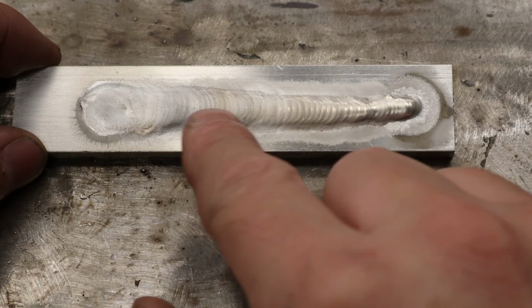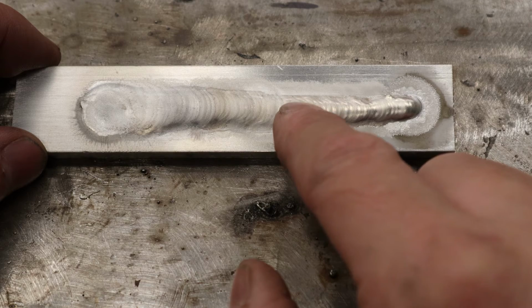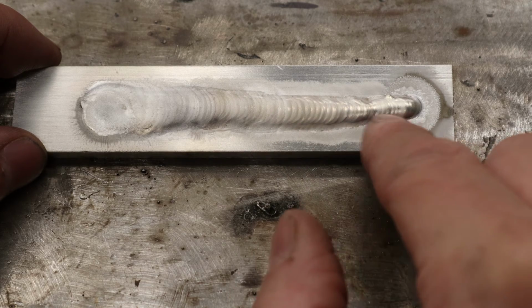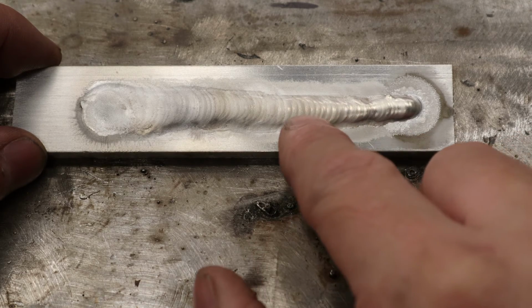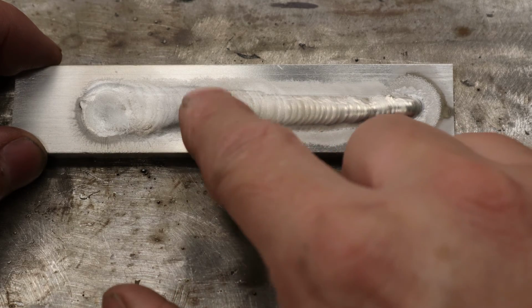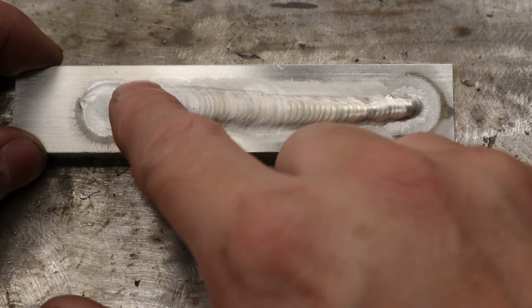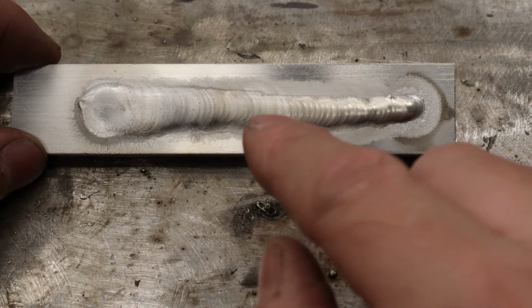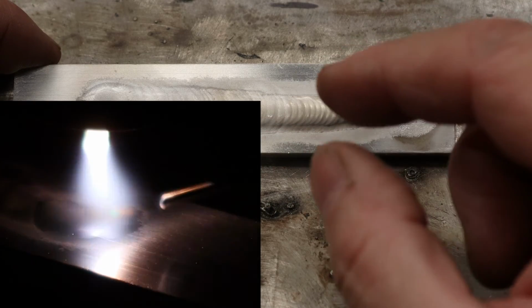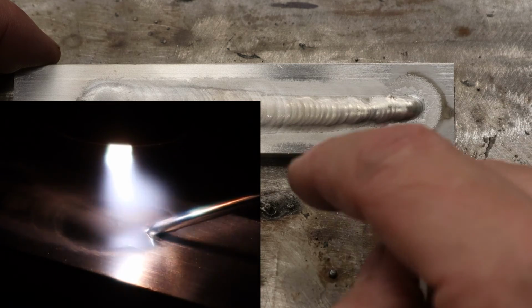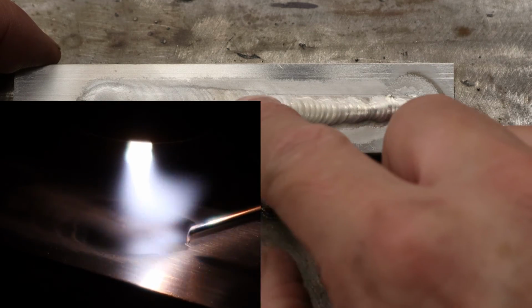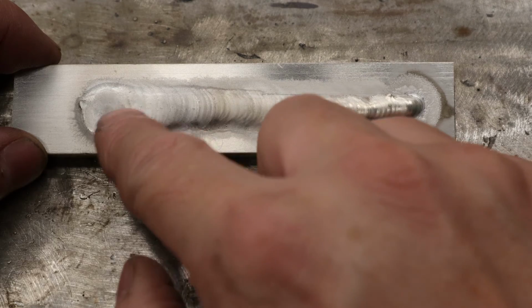And as it starts to go that way, we start to have not as much gas coverage. So you can start to see the shine of the weld start to fade. And it gets a little bit more grainy in here because we just don't have that gas coverage. And the other thing that hopefully the video picked up, there is a little bit of loss of control because the further away the arc has to jump, it starts jumping kind of erratically. And you really do start losing a lot of control back here.